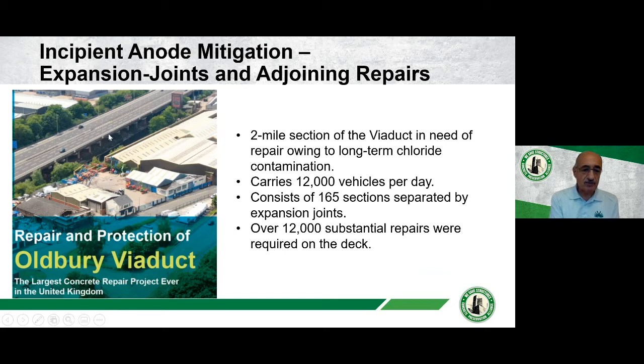They're separated by expansion joints, and the expansion joints were sitting right on top of the cross beams and the columns. So the salt was seeping right down on top of the cross beams and down the columns, contaminating them and causing corrosion. So Highways England carried out a repair of these. And as it turned out, there was a need to do over 12,000 substantial repairs over this stretch of motorway.